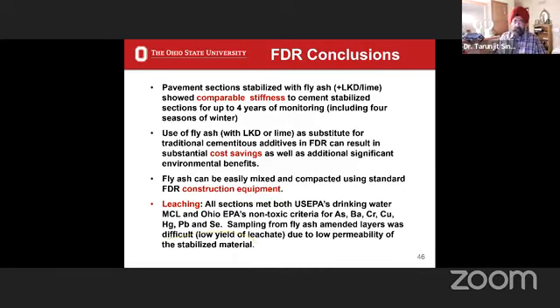And the equipment that was used was standard construction equipment. There was a rototiller, adding water, adding the right amount of lime and fly ash, mixing it well, making sure you provide the right amount of water, not too much, not too little, and then mixing it uniformly is the key. If you cannot mix things uniformly, some places will be too stiff, some places will be too soft. But we use regular production equipment, and we also looked at the leaching, and we saw that none of the elements of concern were exceeded.